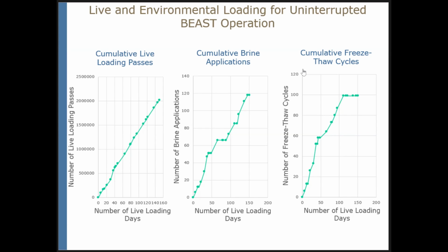So cumulative live loading, there were more than 2 million passes. There were about 120 applications of brine, and there were about 100 cycles of freezing and thawing.